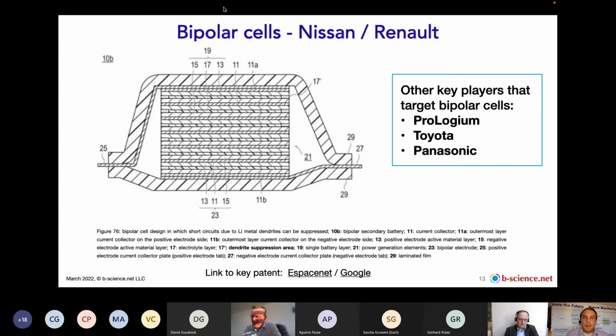Now, the story gets even more complex, but I think it cannot be avoided, because the cell design might also change substantially when working with solid electrolytes. Bipolar cells are very attractive because they could allow for improved energy density at the pack level, because one can make cells based on many electrode pairs separated by bipolar layers that then have already quite high voltages from 40 to maybe 200 volts. And that could facilitate a lot of things at the pack level.